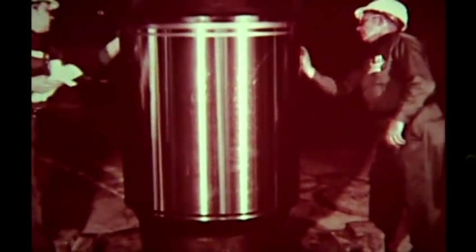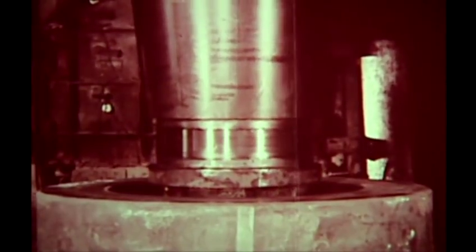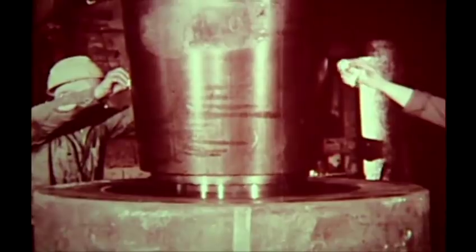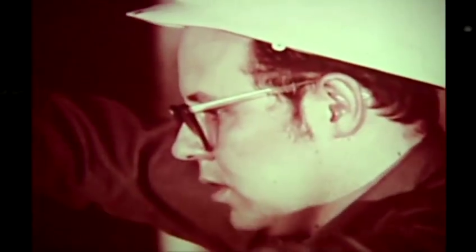Rolled sleeves like this are precision machined and used in a wide variety of manufacturing rolling processes. By using a sleeve over the exterior surface subjected to wear, only the sleeve section needs to be periodically replaced. This mandrel forged sleeve has been heated to the precise temperature which produces sufficient expansion to allow fitting over the roll surface. When the sleeve has been placed over the roll and cools, contraction holds it in place. To remove a worn sleeve, the process is reversed. This exacting process, known as shrinking on sleeves, is another outstanding contribution of the open die forging industry.